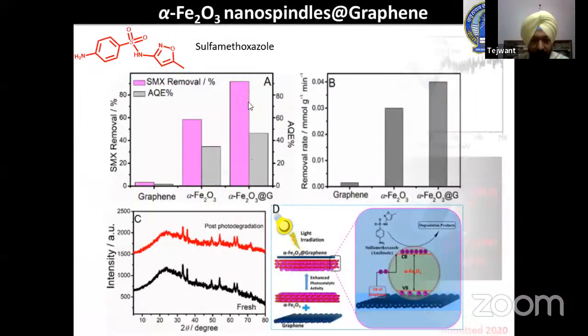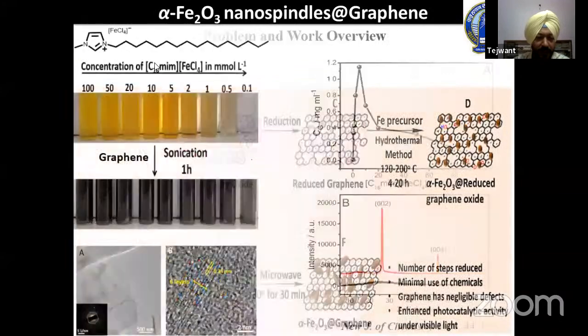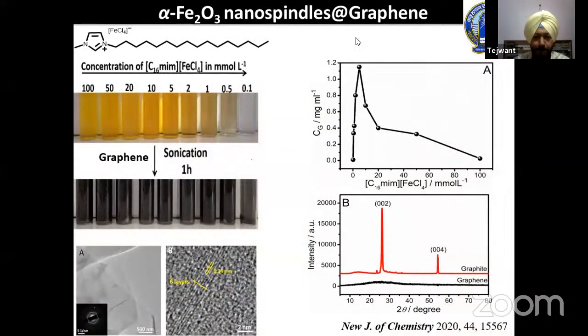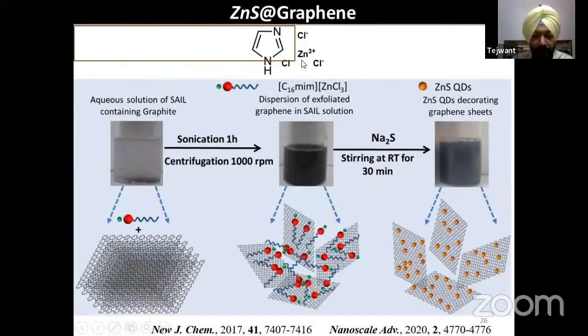So in the last slide, you can see we have used an imidazolium-based ionic liquid having FeCl4 as an ion. From here, we have extracted the iron. We have utilized the Fe present over there for the preparation of nanoparticles. So similarly, we go with another example. Here we have used zinc chloride based same imidazolium ionic liquid, C16MIM zinc chloride. Similar methodology has been adopted.